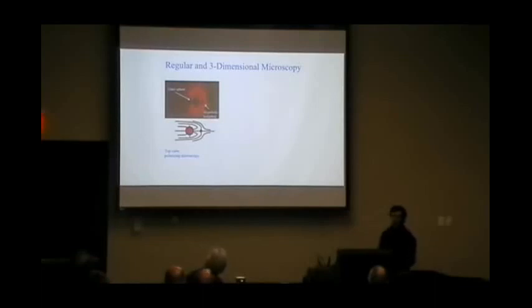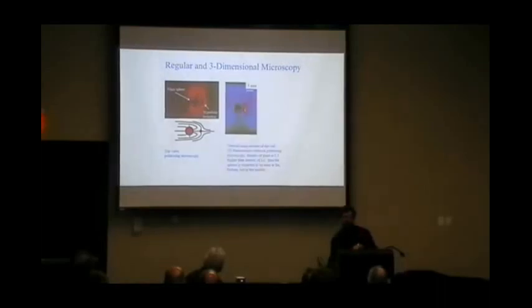Here you see a simple glass sphere submerged in the thick cell of a liquid crystal, and you might see that on the right-hand side of the sphere you have some optical perturbation, and this is nothing else but this hedgehog. Now we have a microscope that allows us to trace the director distortions in the vertical cross-section of the cell, and when you use that microscope, you might see again that there is this perturbation associated with the point defect. But then there is also something strange.